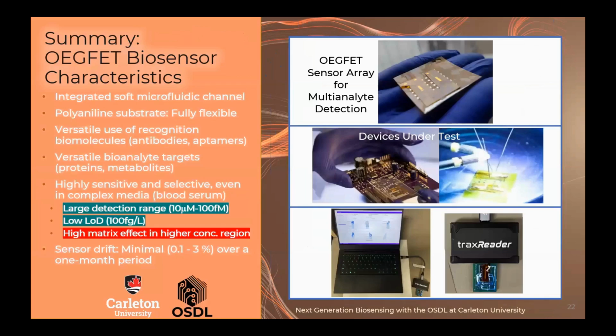So to summarize, with this work, we've expanded the organic electrolyte gated FET footprint from purely an aptamer sensor to a multi-analyte. So we can incorporate aptamer antibody. We can look at not just metabolomic markers, but large size proteomic biomarkers. We have a broad detection range, which fares really well in the lower concentrations because of the inverse current to concentration correlation. We are seeing high matrix effect in high concentration region, which is something that we are investigating in the current study as well, and see if it's possible to push the detection range a little bit more. And the sensor is stable, laboratory shelf life close to a month.